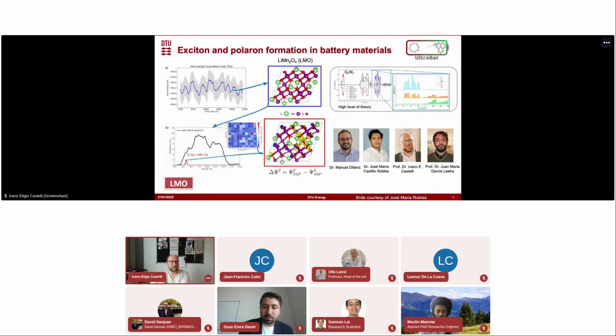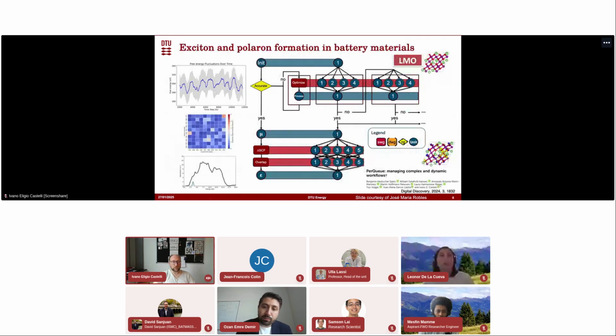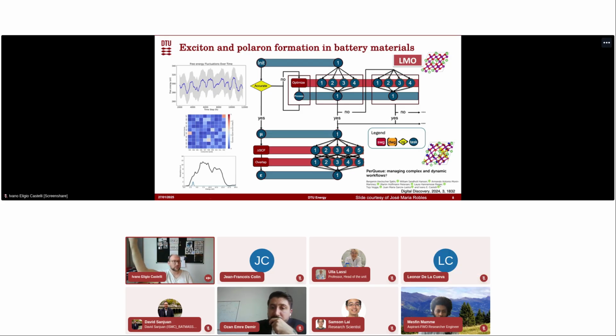And everything starts at the atomistic scale, where we do high-level theory, high-level density functional theory, to understand how the polarons are formed and how the polarons and excitons in general move in the crystal. To do that, we use autonomous workflow managers, which allow us to orchestrate all the simulations by themselves, in an automated fashion, going from the most common relaxation to very advanced simulations, where we calculate how the polarons are really formed and how they move in the system.